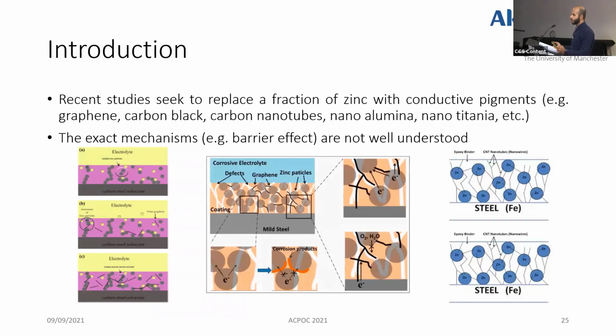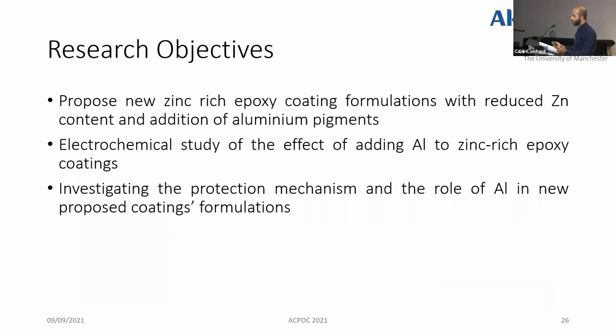So recent studies seek to replace a part of zinc by conductive pigments such as graphene, carbon black, metal alloys, or carbon nanotubes, but the exact mechanism, especially the barrier effect, is not well established. That's why our objectives in this research are to propose new zinc-rich organic coatings by adding aluminum pigments and electrochemically study the effect of adding these pigments, and to investigate the mechanism of protection and the role of aluminum in these new formulations.